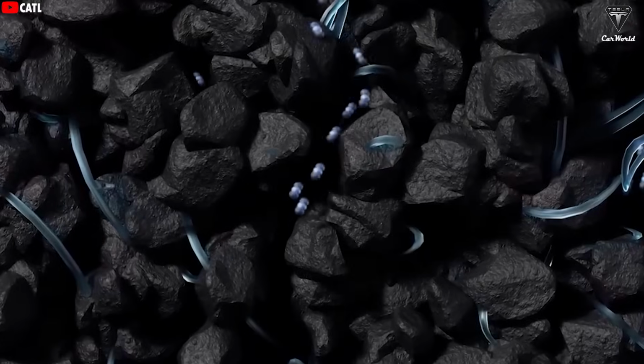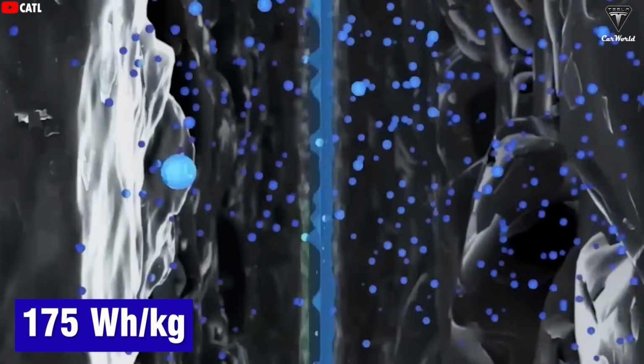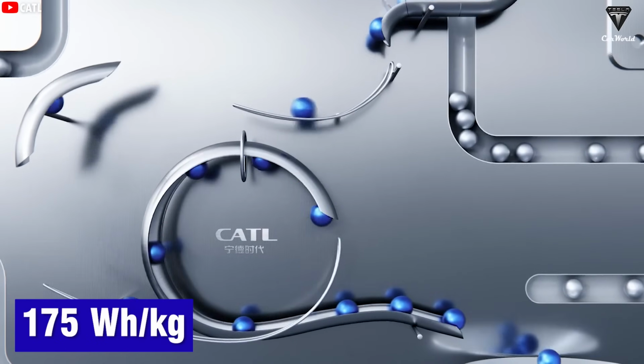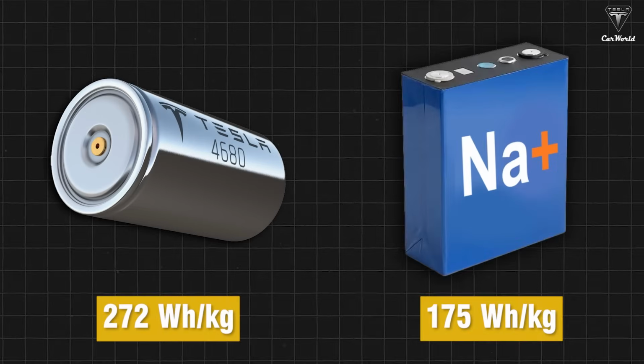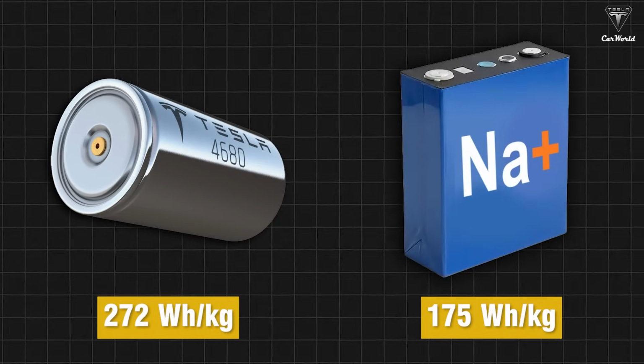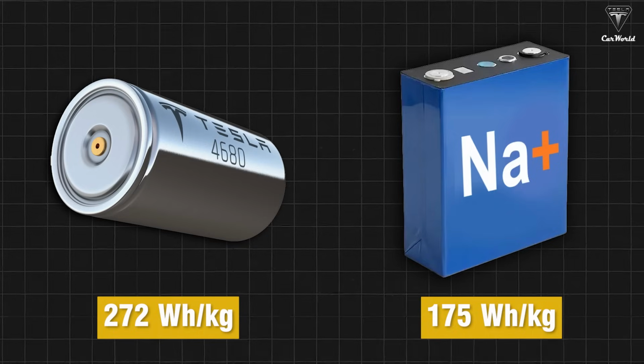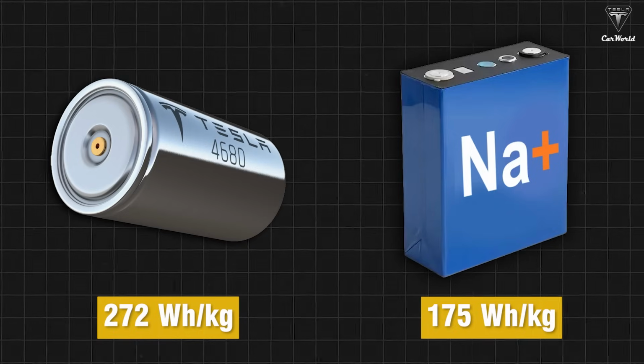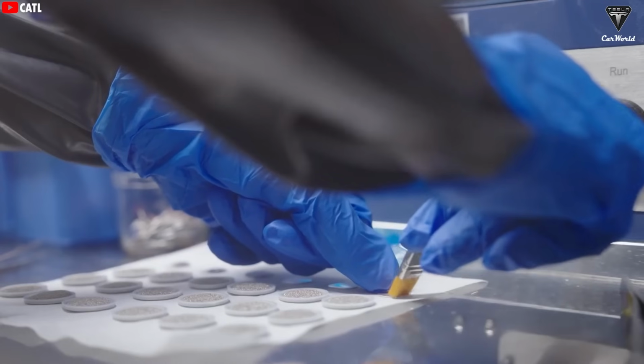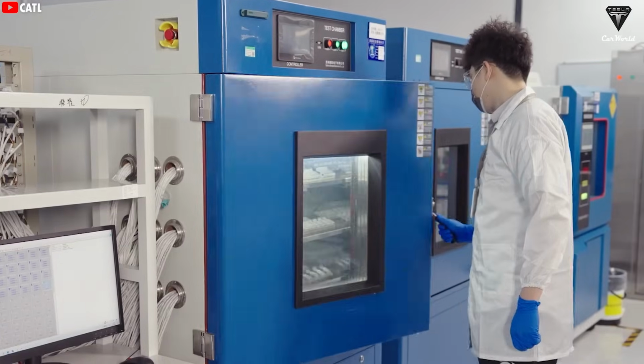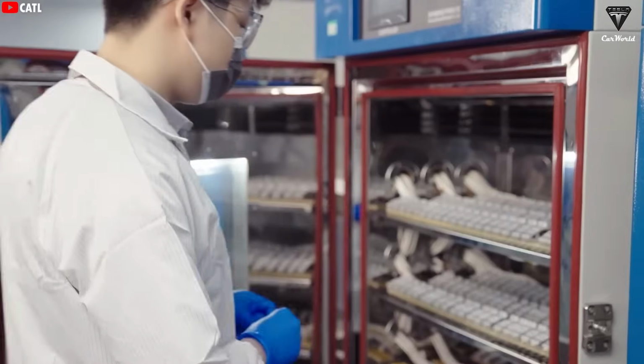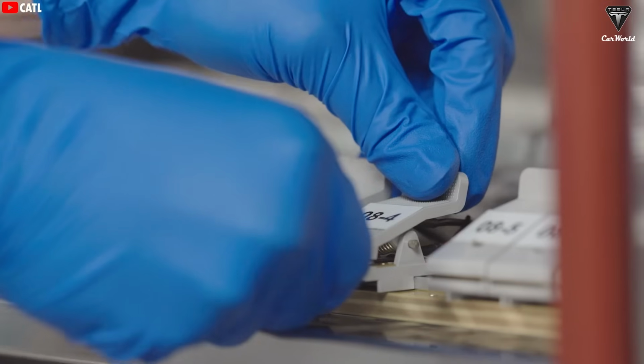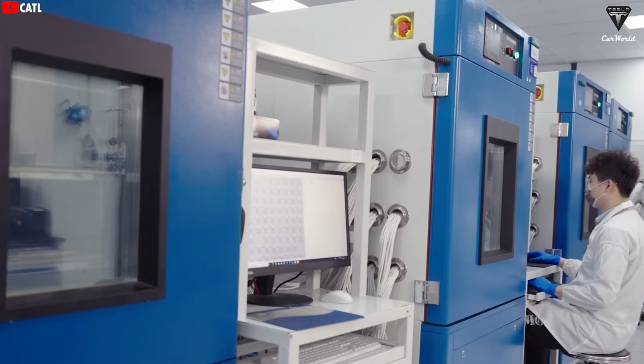Of course, we have to admit that the energy density of 175 watt-hours per kilogram is not an impressive number. Compared to the 4680 battery with a density of 272 watt-hours per kilogram, the Naxtra battery is still quite far away. CATL's goal is that sodium batteries can soon reach 200 watt-hours per kilogram, but at the moment, it seems that this will not happen anytime soon.